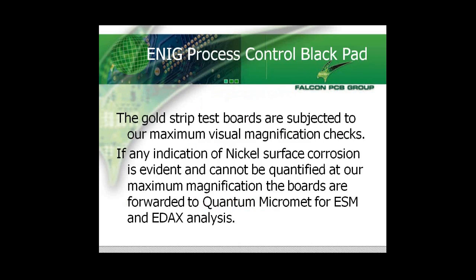On the gold strip test boards, we subject them to our maximum visual magnification, which tends to be between 1.5 and 2,000 times. If there's any indication of any nickel surface corrosion, we will then forward the board to a local laboratory, Quantum Micromet in Buxton, and they will perform SEM and EDAX analysis for us.